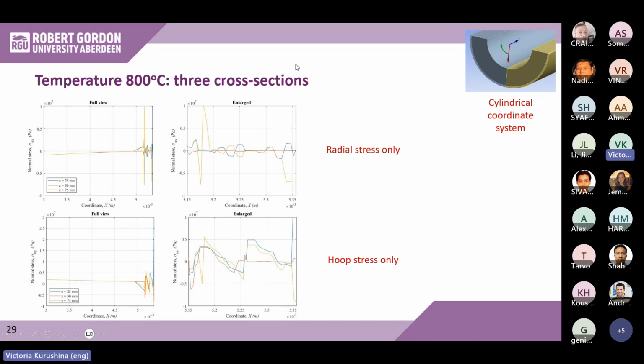If we compare three cross sections, you can see that in terms of the substrate, when we're coming through the titanium substrate, there is not much of a difference between these three cross sections, but there are significant differences already in radial and hoop stresses in between the layers, starting with the first silver interconnect between the substrate and the cathode. You can see this enlarged part here on the right for both stresses.